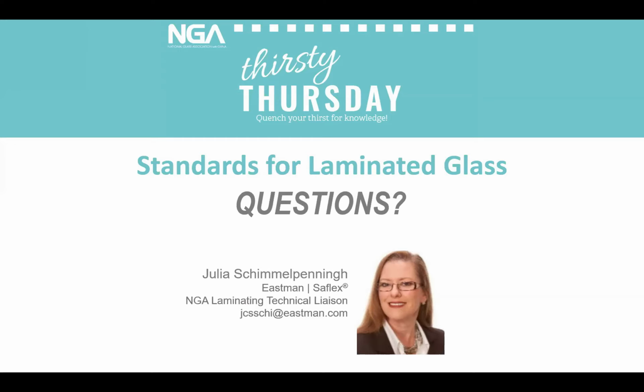All right. In ASTM C1914, why are there two different tests offered, the bake and the boil, within one standard? Because it would seem someone could decide which is easier to pass. Well, and it's in there for a very particular reason. A lot of the products out there traditionally and historically have had absolutely no problem being dunked in a boil tank full of water. However, as products have evolved, there are surface applied materials that can give you some performance levels, but they don't necessarily survive boil. And so therefore you have the thermal portion, which is taken on by bake, and the correlation of bake and boil is pretty well known, and bake is also a very accepted test that shows the proper de-airing and durability.